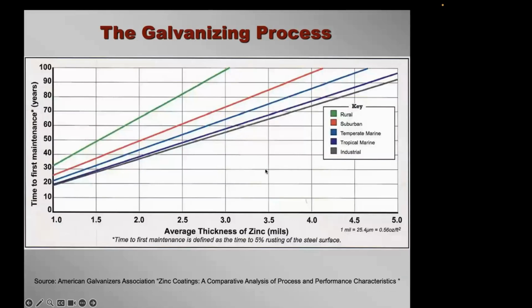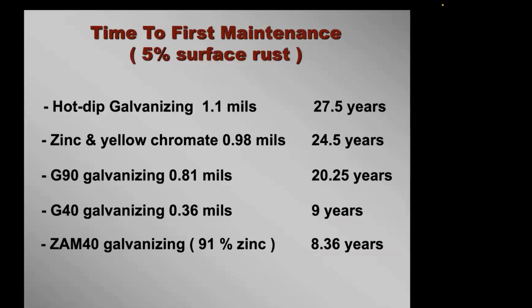So what they go by is what's called time to first maintenance. This is their chart. And the time to first maintenance is defined as the time to 5% rusting of the steel surface. So in a suburban climate, at 1 mil thick, it's going to take about 25 years to get to 5% rust on the surface. So let's take a look at how that translates out to time to first maintenance. So hot dip galvanizing, you get 25 years times 1.1, you get 27.5 years. Zinc and yellow chromate, 24.5 years. G90 at 0.8 mils is 20.25 years. G40 at 0.36 mils is 9 years. And then because of the reduced zinc content, the ZAM40 is 8.36 years.